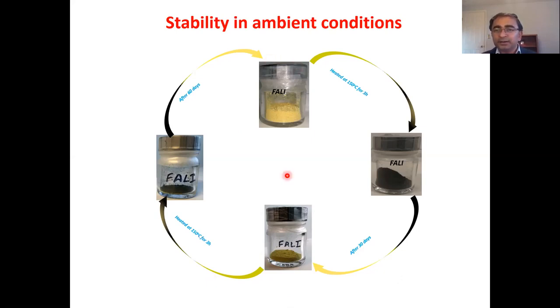if you made a material in bulk form, no problem. In the starting, if you heat it, you will get a black phase. But if you put it for some time and it converts into yellow phase, or some impurities are there due to changes of perovskite into non-perovskite phase, you heat it again and you will get the perovskite phase again. This is the best thing which I will get.